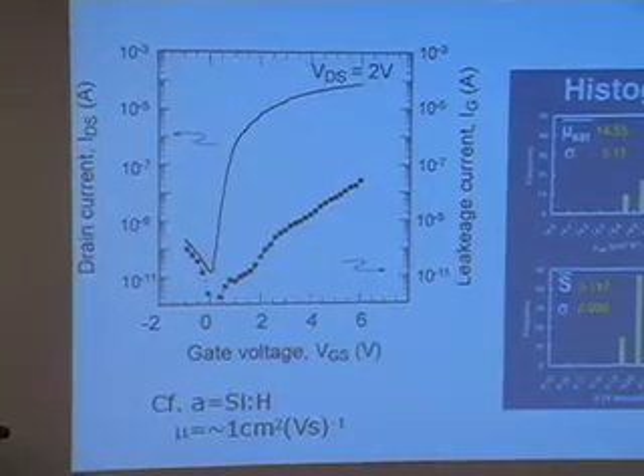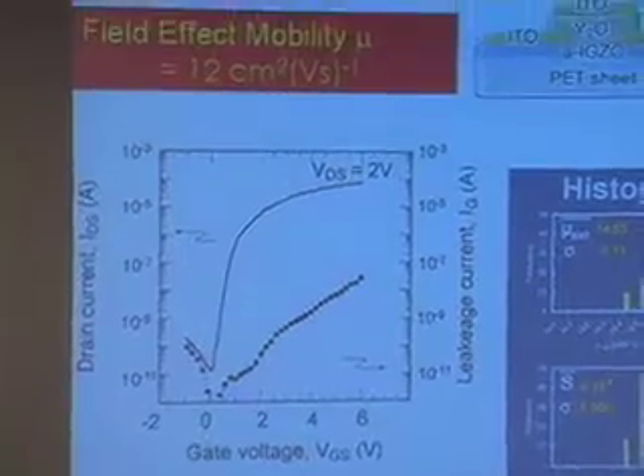The amorphous silicon case is 1, so it's one order of magnitude different. This is with room temperature deposition just by sputtering. By using such a very, very simple deposition process, we can get a one order higher mobility.